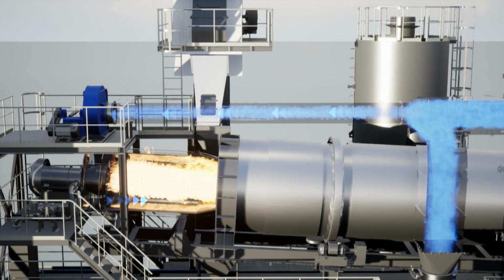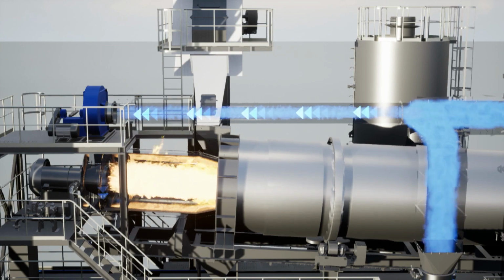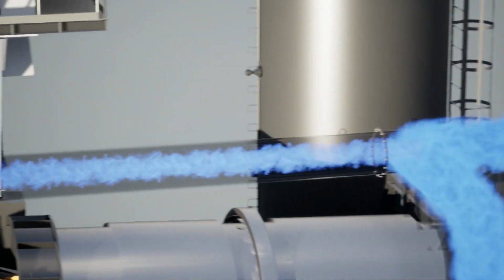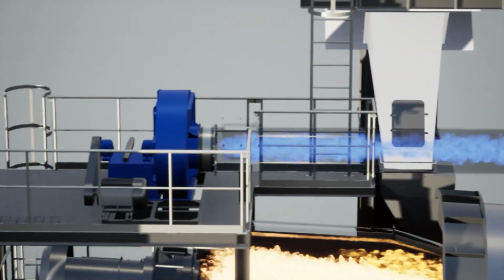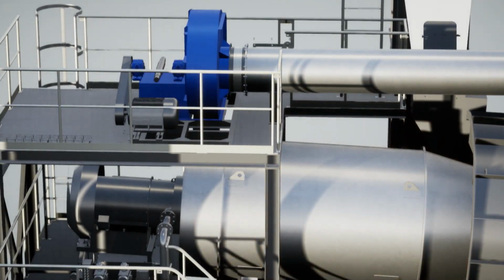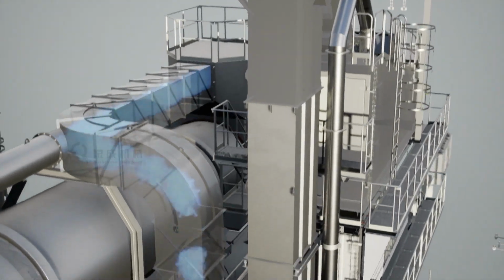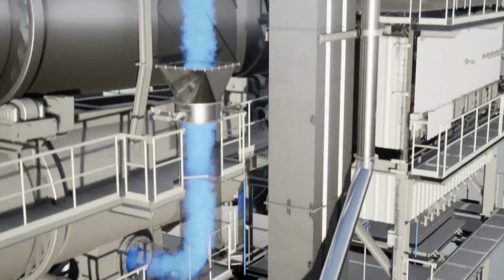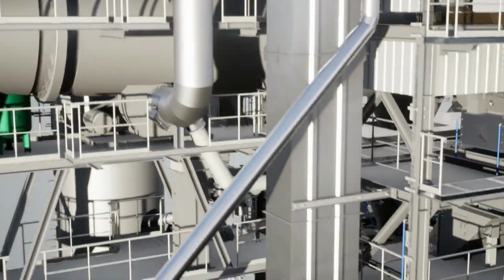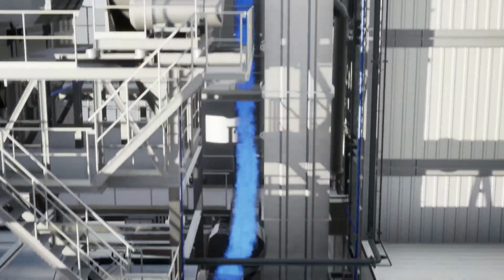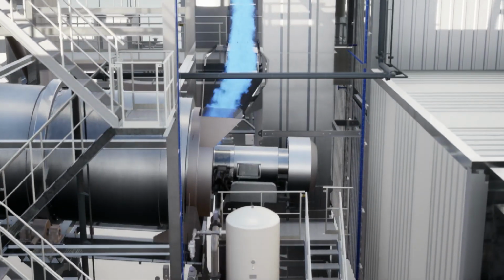The inert gas heat cycling technology introduces the inert gas that produces very low oxygen content after heat transfer into the drying system through a special fan, so that the RAP can exchange heat in an oxygen-deficient state to reduce heat-caused aging. After heating, the exhaust gas of our RAP will contain a large amount of refined oil, which is introduced by a special fan into the raw material drying drum, where it is carbonized after burning, and then discharged after being dedusted by a main bag filter.